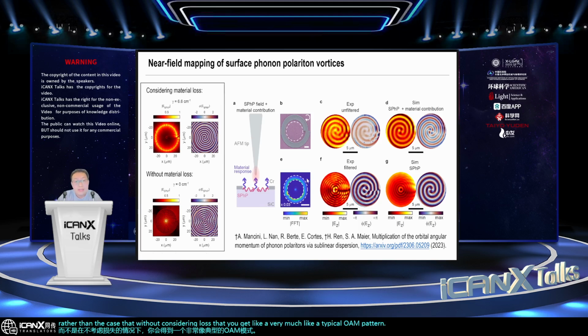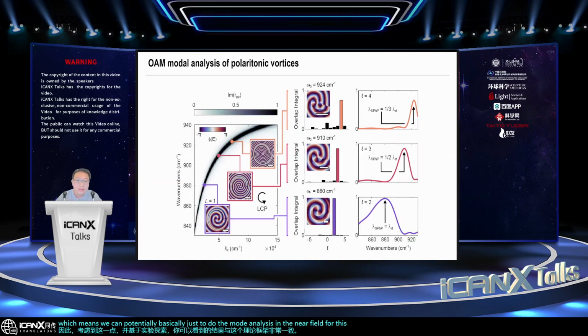With this consideration and based on the experimental probe, the results, as you can see, agree very much with this theoretical framework, which means we can potentially do the mode analysis in the near field for these surface phonon polaritons. And what we observe here is very interesting: by fixing the same single device, same structure, once it's fabricated, everything is fixed.